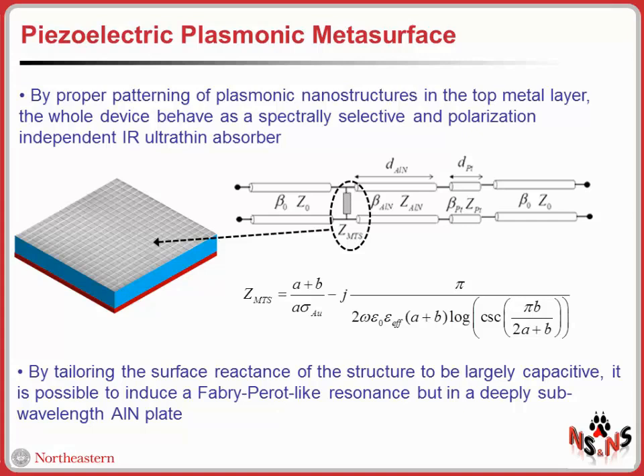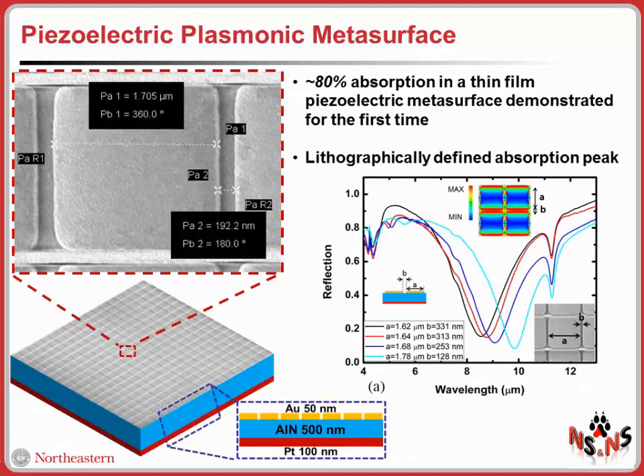What is very interesting here is that the frequency of this electromagnetic resonance, this absorption frequency, depends on the lateral dimensions of these patches, as you can see in this expression here. So it's possible to lithographically tune the absorption band of these devices by changing the dimensions of these plasmonic nanostructures. Here you see some of the plasmonic piezoelectric metasurfaces that we built. We demonstrated that in a 500 nanometer thick aluminum nitride film, it's possible to achieve absorption peaks on the order of about 80%. And indeed, it's possible to lithographically tune the absorption frequency of the structure.